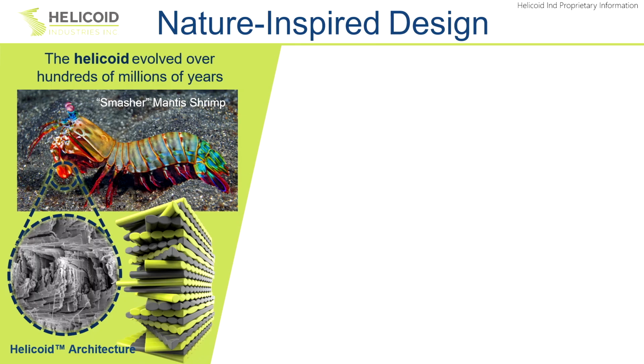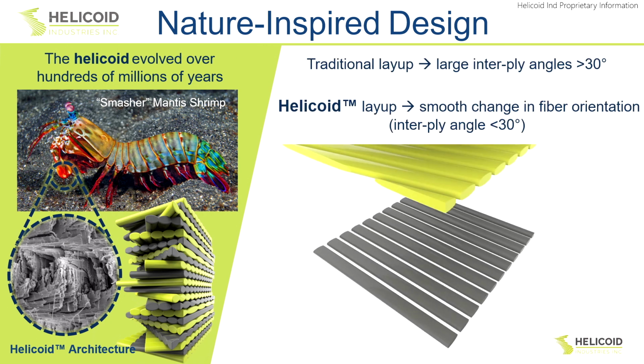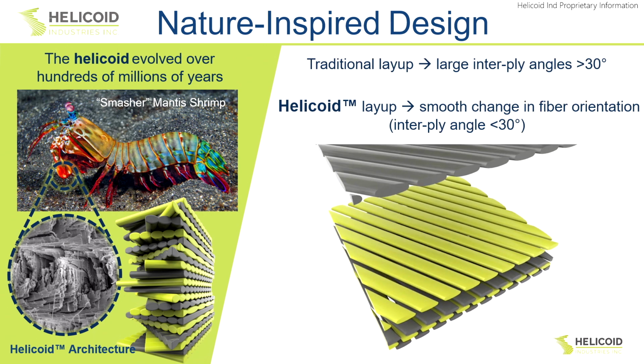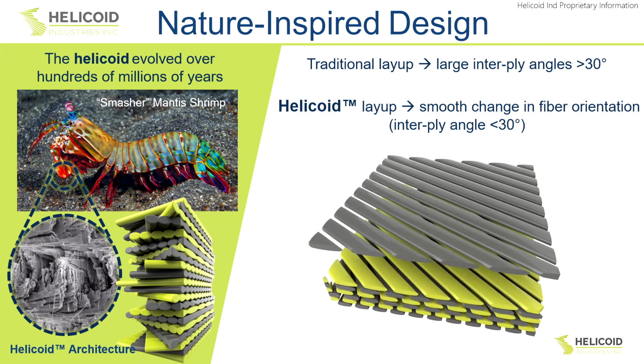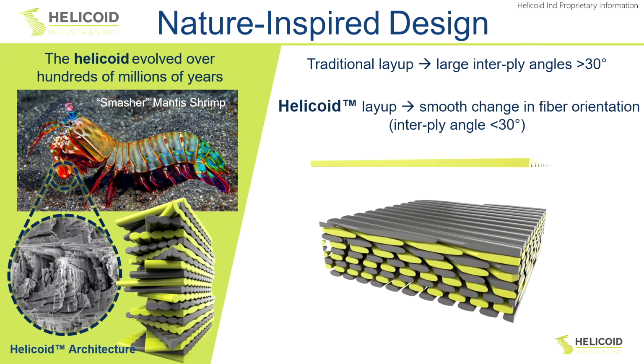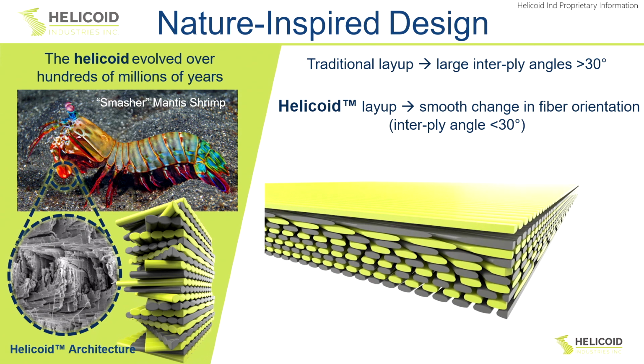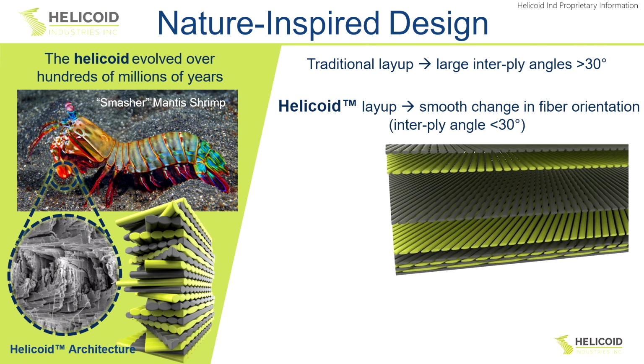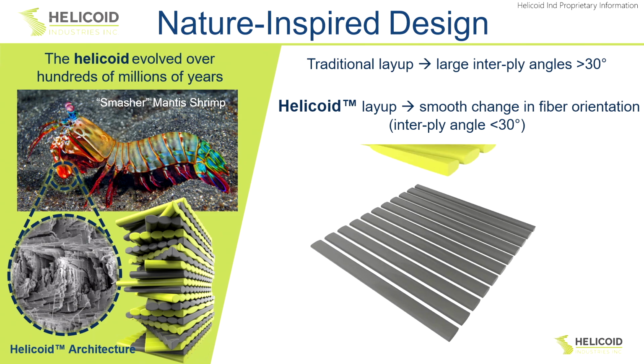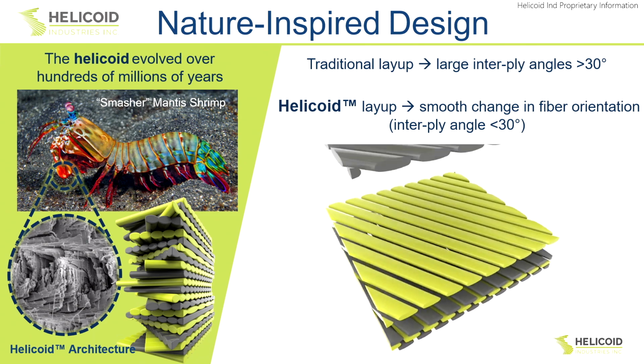And if you look inside the club, in fact, what you observe is that, again, it's fiber-reinforced composite arranged into this helicoidal type of structure. So this translates very easily to a man-made composite, where usually in man-made composites you rely only on a few ply orientations of the fibers when you create your laminated structures. They tend to use very large interply angles, usually larger than 30 degrees, like a common fiber-reinforced composite layup. Quasi-isotropic is at 0, plus minus 45, 90 layup. Very typical, industry standard, too much of a standard.